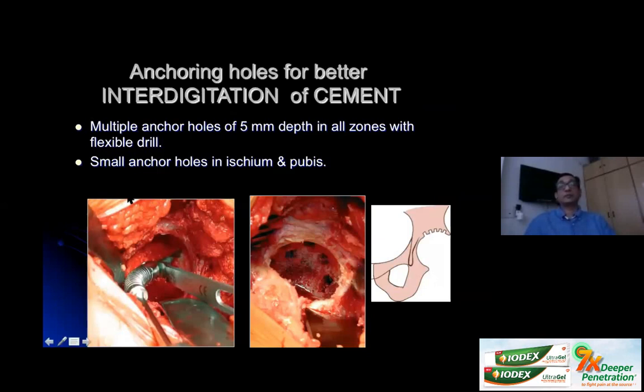The next step would be to introduce the anchor holes. The anchor holes help us achieve a good penetration of the cement into the bone, and which helps us achieve good stability and good hold of the cup. Nowadays, it is recommended that you do multiple holes of about 5 millimeter depth in all the zones. Here, I usually use the flexible drill that comes with the uncemented system, so that you can really go into all the zones and make multiple holes. Generally, about 25 to 30 holes is what I end up with.